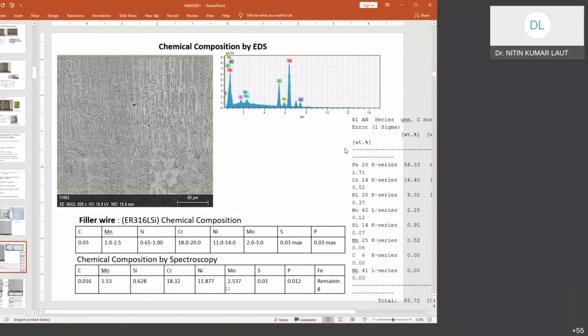And if you try to check the material composition or the chemical distribution of this material, you'll find the components which are supposed to be well distributed are not affected in that sense. For example, if you see this iron component, and again here, silicon is there where it should be. So we could not get any major change of the material property or the material characteristics. That again is a good observation. Despite subjecting the process to a lot of heat and a lot of layers, we are still getting somewhat moderate composition distribution over this layer, specifically the central layer.